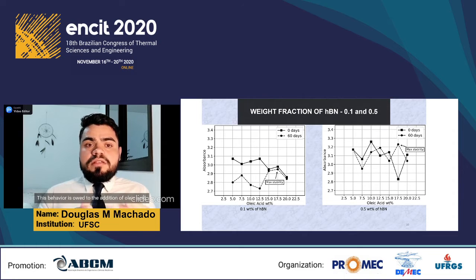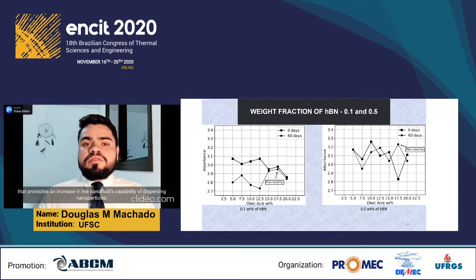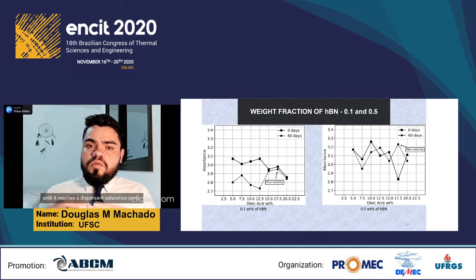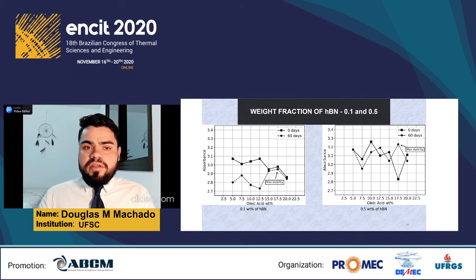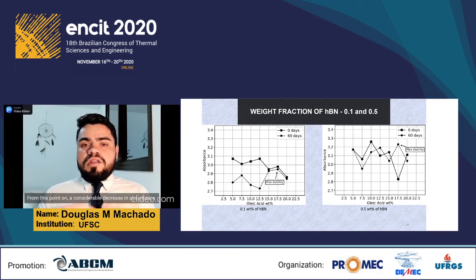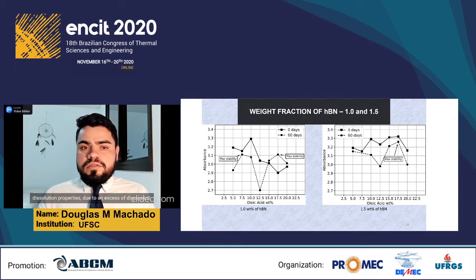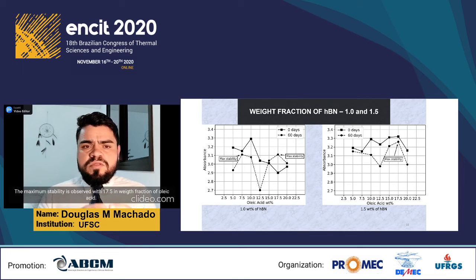This behavior is owed to the addition of oleic acid, which promotes an increase in the nanofluid's capability of dispersing nanoparticles until it reaches a dispersion saturation point. From this point on, a considerable decrease in absorbance is observed, believed to be related to a complete depletion of the base fluid's dissolution properties due to an excess of dispersant. The maximum stability is observed with 17.5% weight fraction of oleic acid.